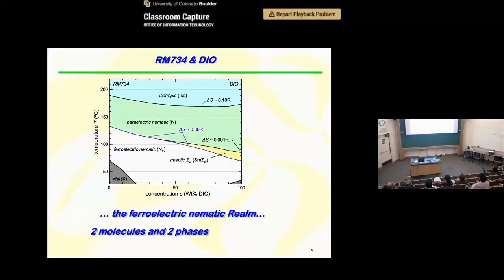The way to determine that is to make binary mixtures of these, and then look at the phase behavior across the phase diagram. And what you see is that the ferroelectric nematic, or this RM734 phase, stretches across the phase diagram. So it's the same phase.